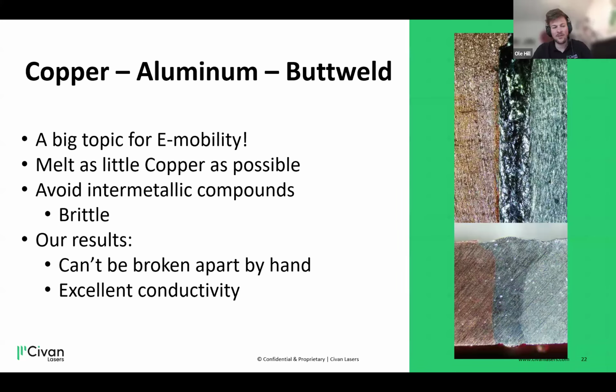On the top right, you can see the surface picture of a small weld between aluminum and copper. What is nice to see is that the weld itself looks almost exclusively like aluminum. In our experience, once you see some bronze in the weld seam, you know it's going to be very, very brittle, and you have melted too much copper into the mix, and then you get intermetallic compounds, which are very brittle. So the goal is to melt as little copper as possible. But you want to avoid a situation where it's only brazing. We have seen this as well.